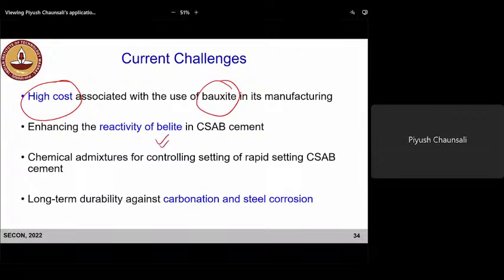Reactivity of belite, because belite content can vary and can also be in significant amounts in these cements, and we know that the belite C2S phase is not very reactive. How do we enhance the reactivity? Okay, that's a current challenge. Chemical admixtures for controlling setting of rapid setting CSA cement is also currently being researched.